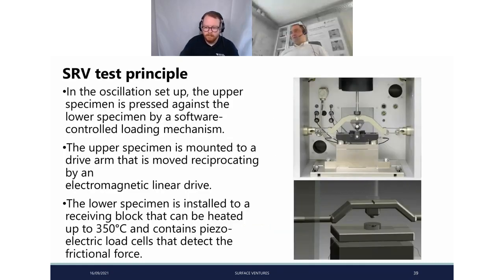Just to show you shortly the test principle in the SRV. You have a loading device which applies a normal force from the top. On the left-hand side of the test chamber, as you will see later in the video demonstration, we have a linear actuator, which is free from mechanical wear. It's electromagnetically driven, so you don't have wear within the actuator, neither friction nor vibrations. So you have a very smooth and straightforward actuator. The upper specimen is moved by this actuator, and the lower specimen is kept static.